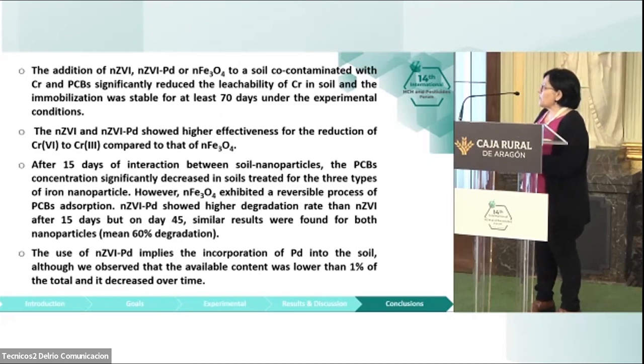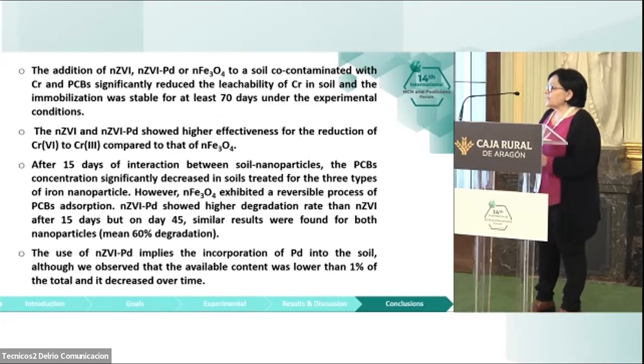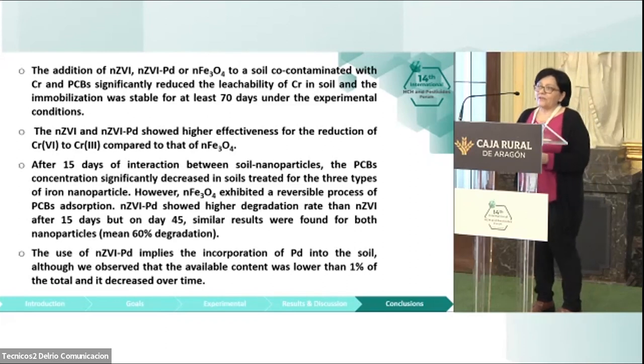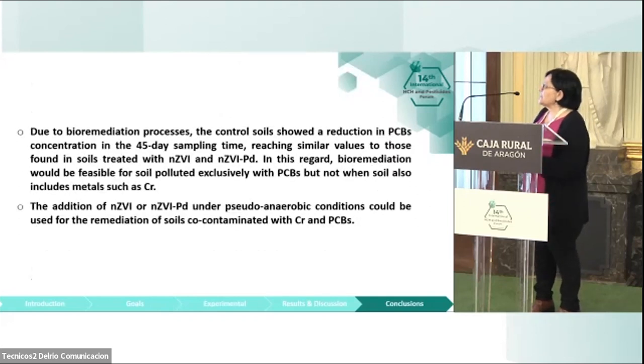After 15 days, the PCB concentration significantly decreased in soils, but in the case of nanoparticles, there is a reversible process, and this wouldn't be adequate for the treatment. And finally, the use of nanoparticles with Pd implies the incorporation of palladium into the soil. So we need to observe whether this concentration is okay or not.